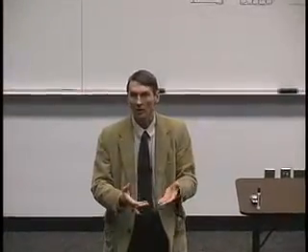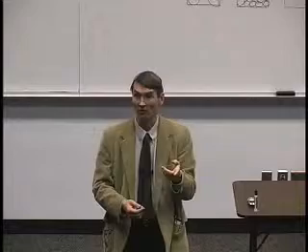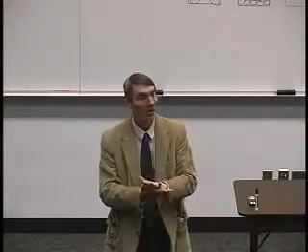It goes from very fines, kind of dusty stuff almost, down to, or up to, depending on the way you think about it, quarter-inch aggregate. So from quarter-inch all the way to fines would be a mix of concrete-type sand, not beach sand. You do use non-graded sand in mortar mixes for a very different reason, because it being all the same size, it makes it much more workable.